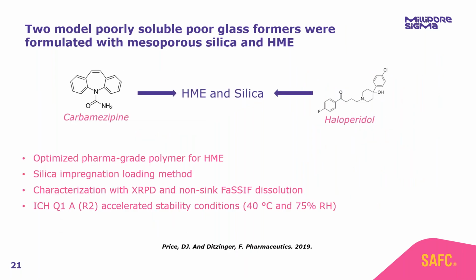So that's what we set out to show. We selected 2 extremely poor glass formers, carbamazepine and haloperidol, and we formulated both of these poor glass formers with hot melt extrusion and with mesoporous silica.